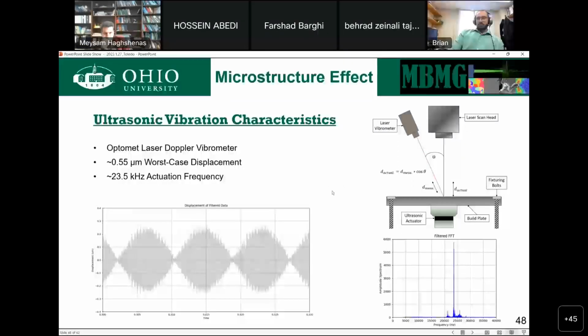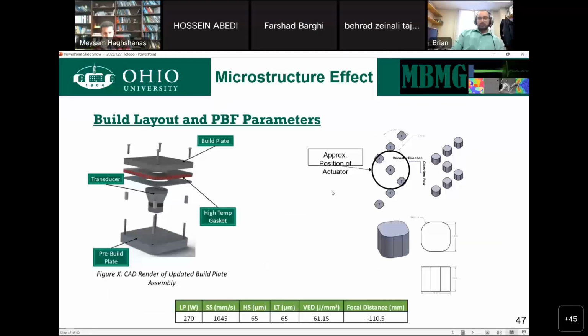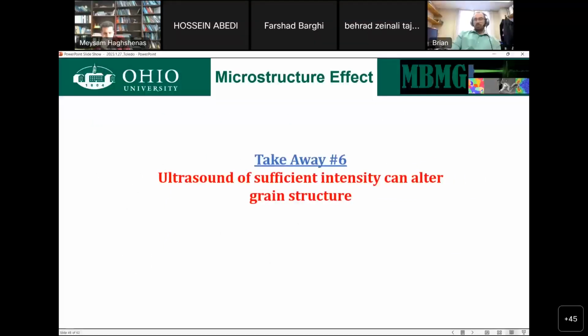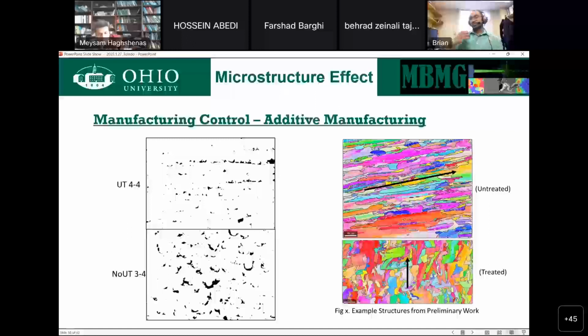If we do that, then we want to see, does ultrasound do this? And what we've discovered is that if you can supply sufficient energy, you can cause a shift from untreated elongated grain structure, with the black arrow representing the build direction, to a more equiaxed grain structure in that direction with a reduction in porosity as compared to no treatment.